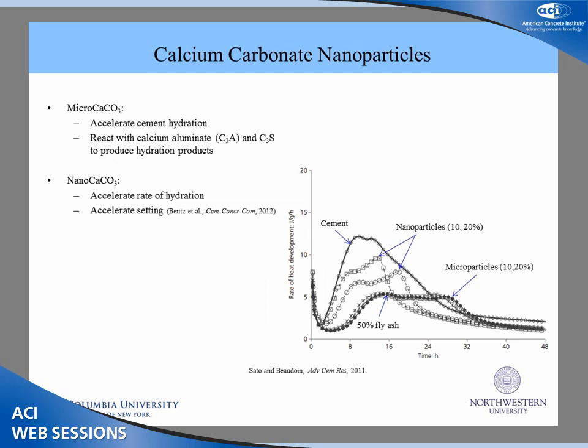So the reason we chose calcium carbonate, Dale Bentz talked about this a little earlier in the session, is that it's been demonstrated that it can accelerate cement hydration, and it can also contribute to chemical effects where it reacts with calcium aluminates and tricalcium silicate to produce its own hydration products. And this has been demonstrated with nanocalcium carbonate particles as well. In this study by Sato and Baudouin, in 50% fly ash cement paste, with the addition of microparticles at 10 and 20%, there was no measurable difference. With the addition of nanoparticles at 10 and 20%, there was an accelerating effect. And similar results were attained by Dale Bentz to accelerate setting.